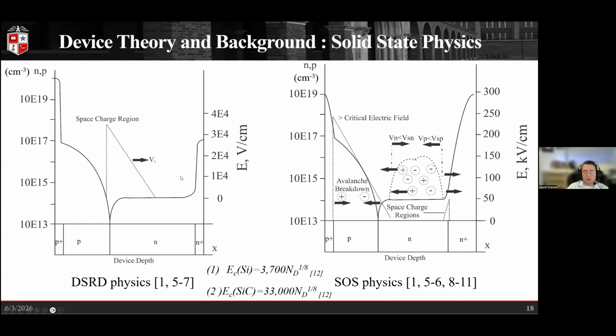So with the DSRD, being that we have no carriers left in the device, we begin to expand that space charge region extremely fast and hold off a very high amount of voltage. By contrast, with the SOS, we begin to increase that electric field. We still have carriers in the device, and so we're going to leak some finite amount of current, slowing down our interruption time. We also eventually will hit the critical electric field, leading to some small avalanche breakdown in the device, basically curtailing the last bit of current cutoff for the SOS device.